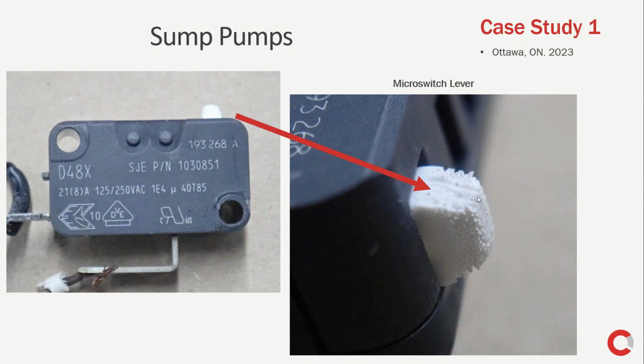And if we look at the close-up picture, the magnification here on the right, we can see the appearance of that plastic lever has changed, and it looks like popcorn basically, and that tells us there's been some type of degradation to it. And this is very interesting because it's a polymer that's encapsulated in a sealed float switch. So there's no water or any other elements going in or out. And so there's a question as to what caused that and whether it is a manufacturing issue or something else.